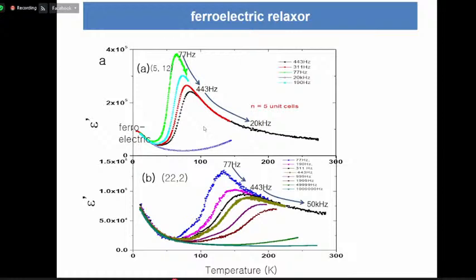We also measured some dielectric constant like this. Then it shows frequency dependence. As the frequency increases, the peak shifts toward higher temperatures. And at low temperature, there's no frequency dependence.